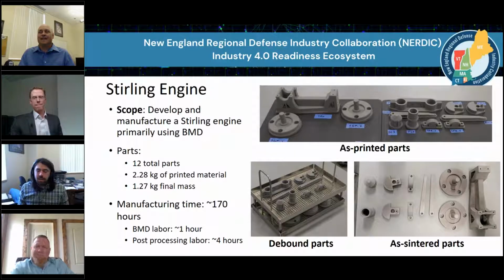That was just simple tasks like setting up the slicing through Fabricate, which is the Desktop Metal slicer that Bound Metal Deposition uses, and unloading and loading the parts into the next machine as you go through the process. After they were sintered, they were then post-processed using some pretty common subtractive techniques. So some of these parts were turned and just polished up to meet tolerances that were necessary for the Stirling engine to run. And that took about 4 hours from the people who were doing that labor. So we can go ahead to the next slide.